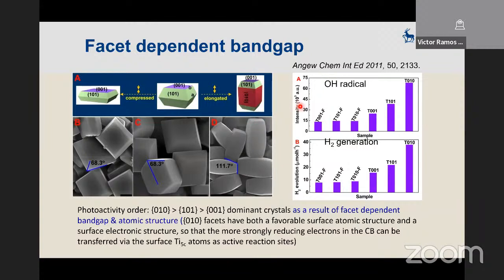And we found for hydrogen production, in particular, the hydrogen production from water splitting, the 010 phase is more favorable, has the highest photoreactivity compared to the 101 phase and the 001 phase. And because of the favorable electronic structure, and therefore enhancing the transfer of the strong reducing electrons on the conduction band, it will accelerate the hydrogen production.